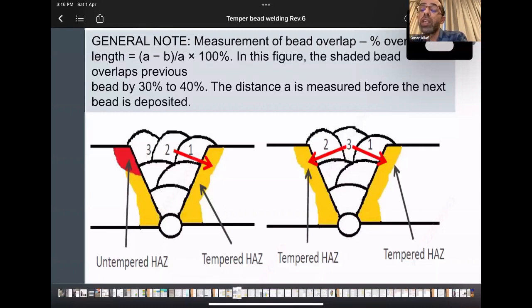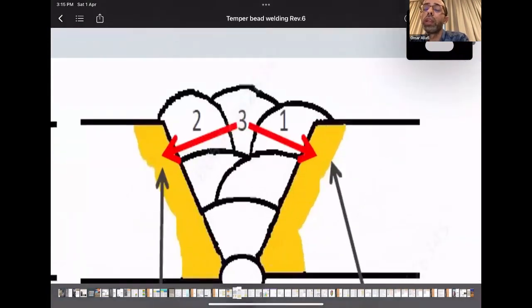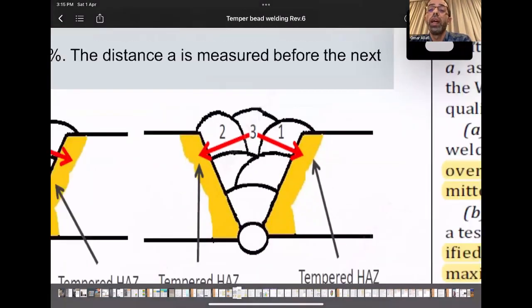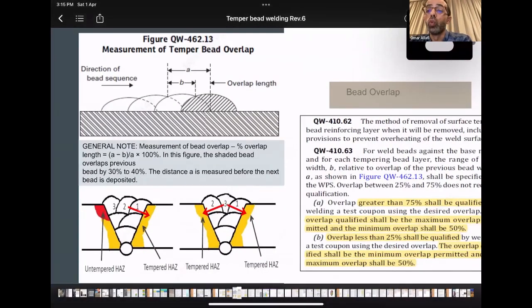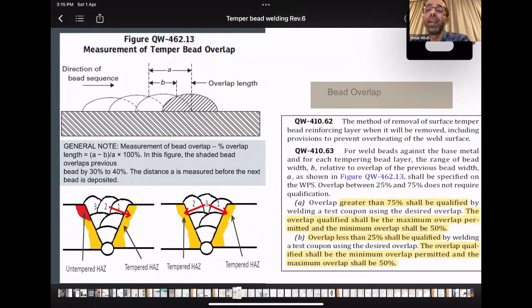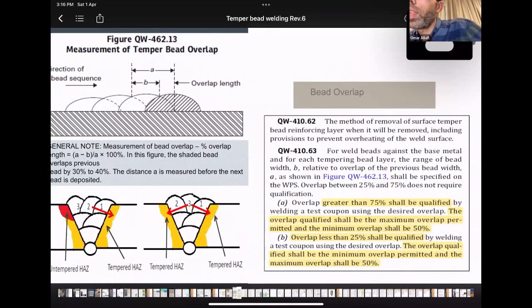So the sequence should be similar to this: 1, 2, and 3. And 3 is supposed to temper the heat affected zone of weld number 1 and number 2. And this is where skill and experience is required. This is why temper bead is very difficult. You don't need only competent and skilled welders, but you also need experienced welders who have experience in temper bead when using this technique. So for the qualification, when you want to have an overlap greater than 75,